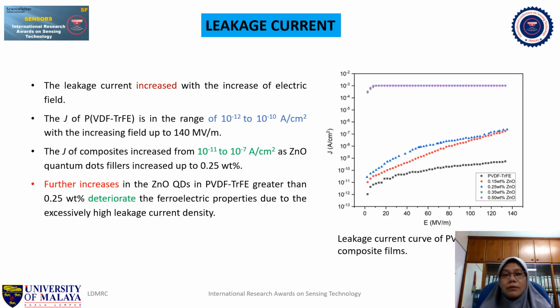In order for us to understand why 0.15 weight percentage of zinc oxide inside the polymer host gave the highest energy density, we have performed leakage current measurement. So the result is shown in this figure here. So what we see is the leakage current increases with the increase of electric field, as shown in the figure. The current densities from all the compositions range from 10 to the minus 12 to 10 to the minus 10, with increasing field up to 140 MV per meter.